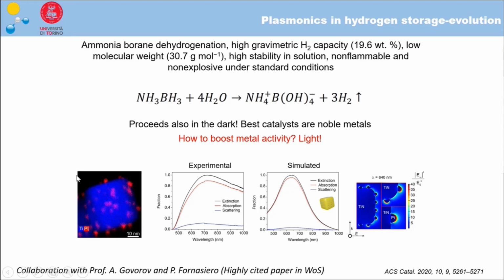And in this case, as I mentioned a few moments ago, we use nanocubes of titanium nitride decorated with platinum nanoparticles for hydrogen evolution. In particular, we use it for the dehydrogenation of ammonia borane, which is a chemical of interest to be used as a hydrogen storage material. As you can see here, many materials can evolve hydrogen from ammonia borane, but using light we can have much increased rates of hydrogen evolution.